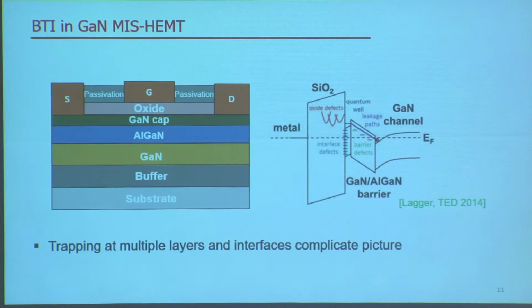So let's come back and look at the BTI in gallium nitride MISHEMT. I talked earlier that we don't quite understand the physics behind it. What is the reason for that? Well, it's mainly because, as you can see in the cross-section here, there are multiple layers and interfaces, and that makes the picture quite complex. On the right-hand side is a recent work studying the threshold voltage instability in MISHEMTs. The authors in this work suggest there are trapping sites inside the oxide, at the interface, as well as in the barrier layer. And it's very difficult to separate the effect of each of them on BTI.